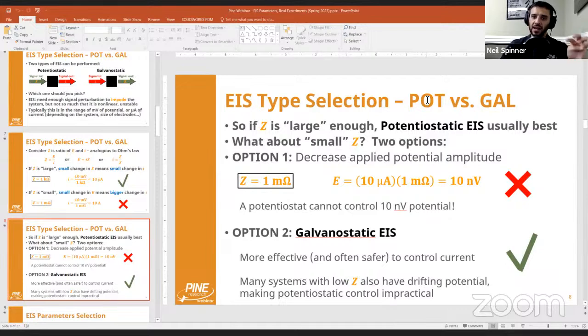The potentiostat cannot do that. It has to measure OCP, which is a passive experiment, and then it has to apply that measured potential. Now, it's just not really possible for any potentiostat to measure OCP, which is like a hands-off experiment, where you're not applying anything, you're just measuring open circuit, and then apply that exact potential. But if the OCP has shifted ever so slightly, you might be ever so slightly applying a positive or a negative overpotential, something like that. Whereas with galvanostatic impedance, you're modulating the current. And because you're measuring the potential, it's sort of implicitly superimposing the signal on top of open circuit, which to me makes it better in a lot of ways in that you guarantee you're where you want to be.